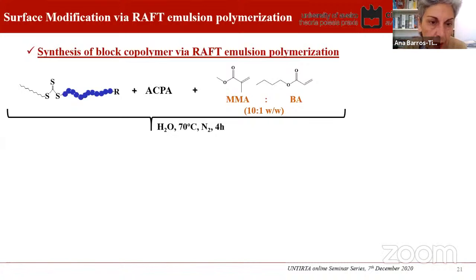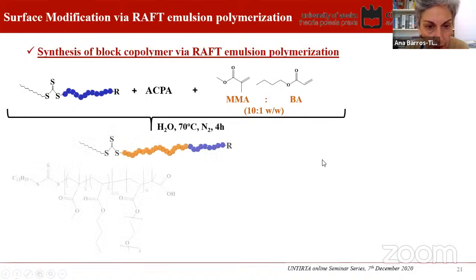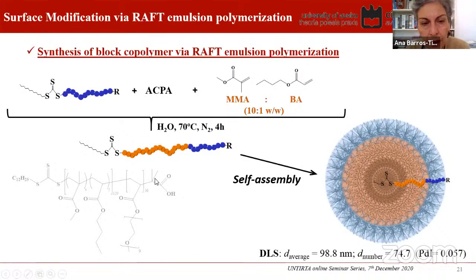From the macro RAFT, we also prepared this block copolymer, now in emulsion polymerization, again using ACPA, but now adding the methyl methacrylate and butyl acrylate as hydrophobic monomers to yield this copolymer that, as it contains a hydrophobic part and a hydrophilic part, can self-assemble and actually make nanoparticles, so small structures with sizes around 100 nanometers.